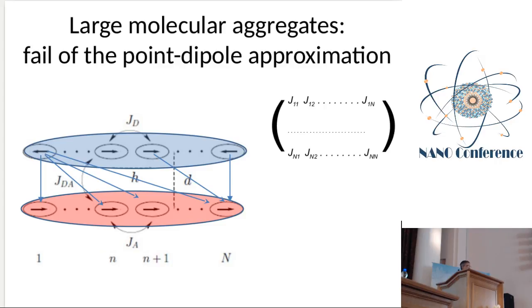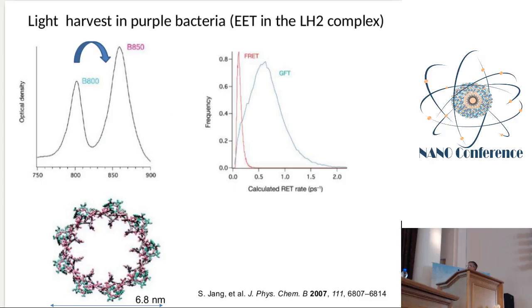That means that there are many channels through which the energy can be transferred. For example, if we have the dark state here, when dipoles are antiparallel, energy cannot be transferred between these dipoles. Energy can be transferred from the other dipoles to this point. And that means that in large J aggregates, we have a specific situation when energy can be transferred through additional channels, and energy can be transferred faster than Förster theory describes.